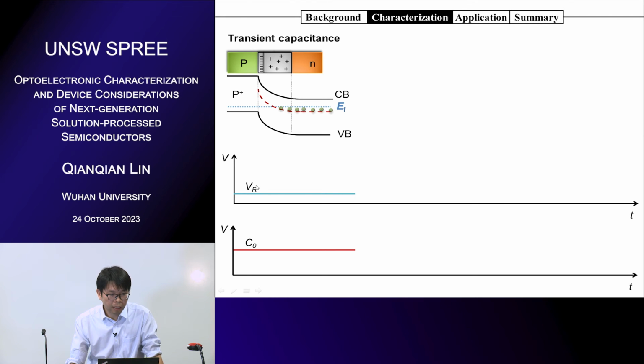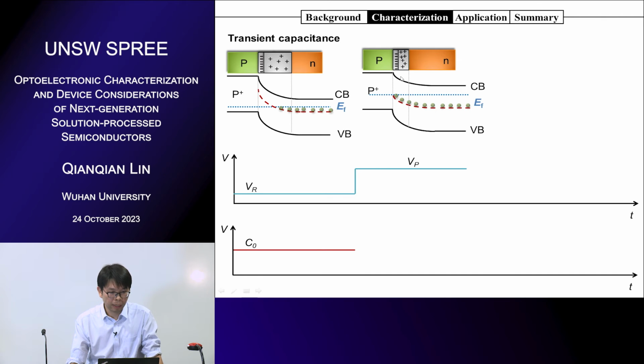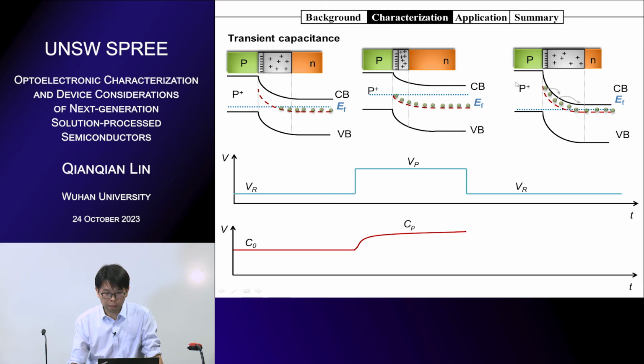So if you look at steady state under reverse bias, the capacitance will be constant. If you give a positive pulse, the band bending will be reduced and the carriers will be injected, right? So with the band bending reduced, the energy level of the traps will be lower than the Fermi level, and all trap states can be filled. And you get a slowly changing capacitance under the forward bias. And if you remove the forward bias immediately, you will also get a picture like this.